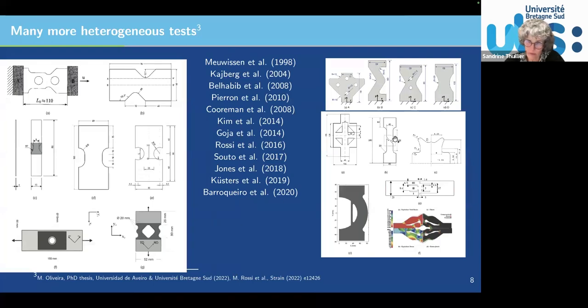And there's also a different approach, which is using optimization. You could, by shape optimization, obtain a geometry. So you take an indicator and you try to maximize the heterogeneity. So, for example, the strain range, you want to have both small and large strain during your test. So you try to promote a large range of strains, but also strain paths. So by defining these several indicators, you may end up with a geometry by shape optimization. And I would say more recently, people have also tried topology optimization in order to design a good shape.